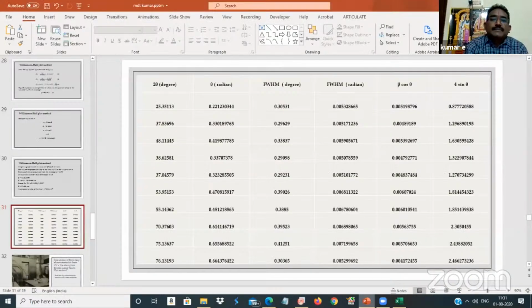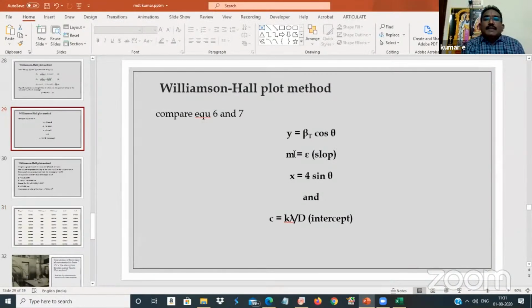From the box we get the slope, 144.216, then the intercept, 0.96. So from this straight line fitting, we got the slope and intercept. These values are used in the WH method to find the exact crystal size. So we draw the graph between beta t cos theta and 4 sin theta, plot a straight line fit, and get the y-intercept and the slope.